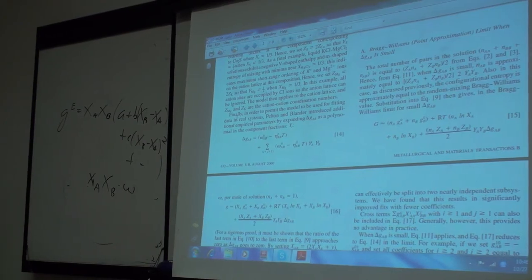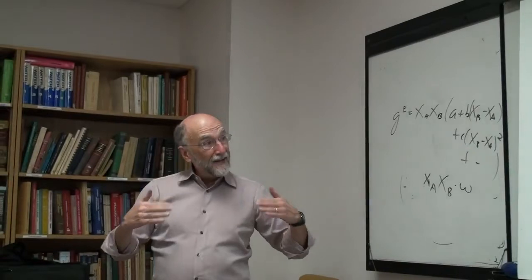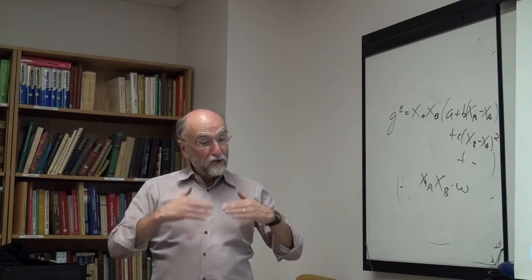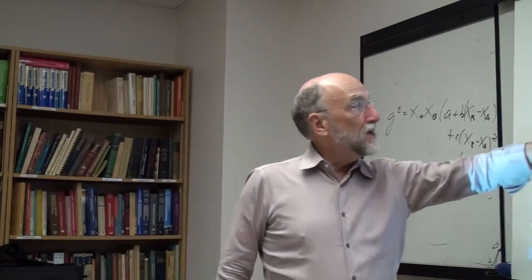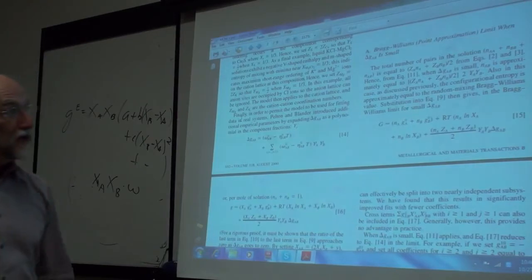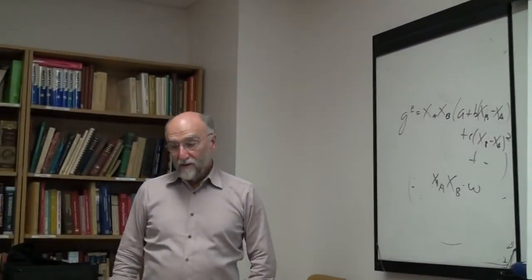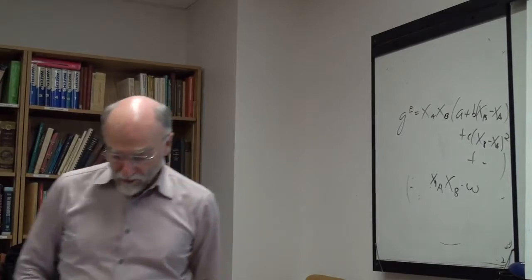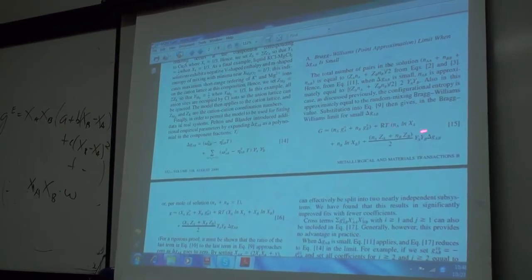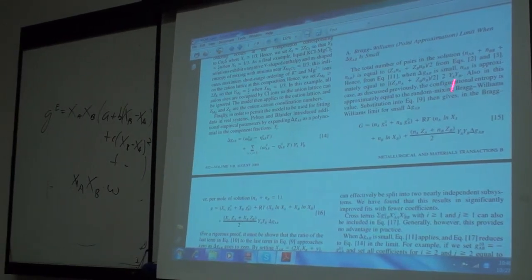Okay. So what's happening is that as the system approaches ideality, as delta G becomes smaller and smaller, the distribution becomes ideal. The NAB approaches simply 2XAXB, and the whole thing reduces to the polynomial model. The delta GAB expansion here is the same as the delta GAB expansion we use in the polynomial model. So even the coefficients are the same as long as you account for the NZ over 2 term.